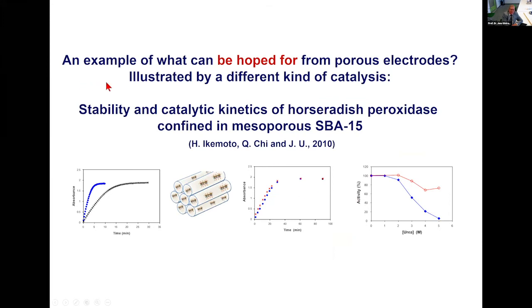In the way of what we hope to achieve by using nanoporous material, I'll show what one could perhaps hope for. This is a non-electrochemical system. Horseradish peroxidase trapped in mesoporous silica material. Just to show what can happen. If you have the enzyme in solution, that's a certain enzyme activity. Then you heat it to 70 degrees Celsius, cool it down, and measure it again. And then you can see it has somehow destabilized.